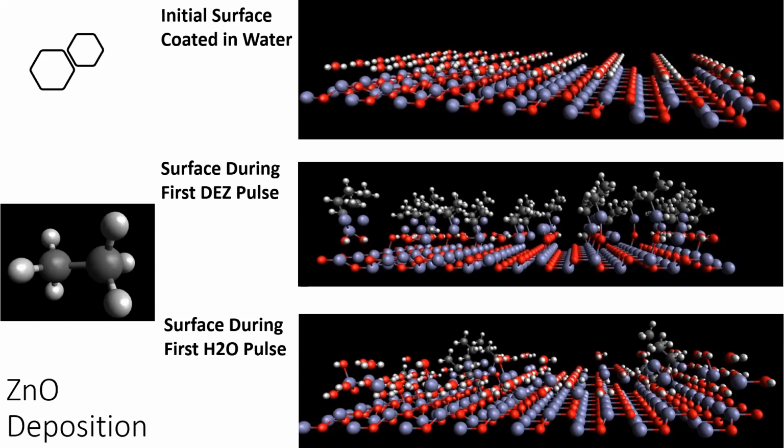For the remainder of the pulse, these oxygen atoms will basically trade hydrogens back and forth in a process called proton diffusion. So basically, after DEZ is formed, these atoms play a molecular hot potato until the next pulse. We'll purge, and then we have an H2O pulse.